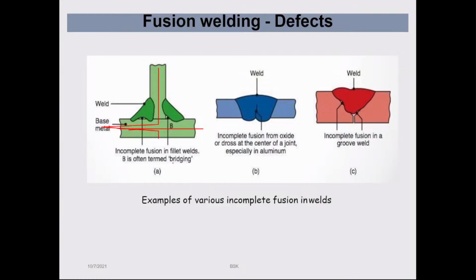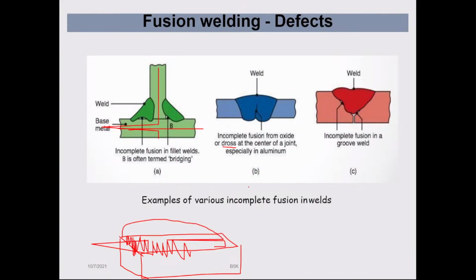So B is often termed bridging, right? This one is called bridging. That term is used for that sort of problem. Then the second one is incomplete fusion from oxidized dross at the center of the joint, especially in aluminum. So let's say due to oxidization, it retained some kind of impurity. You know that when you melt things like aluminum, something forms on top. We call that slag, and the term most used for it is dross. That is, oxidized aluminium floats on top. If you use that molten aluminium for melting, sometimes these dross may get into empty spaces. So that may cause an incomplete fusion.